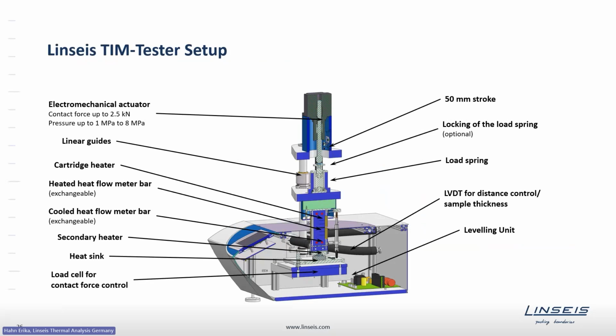On the slide you can find a more detailed sketch of the TIM tester with its components. The main part here are the meter bars, which contain heaters inside, being able to heat up the sample. In between, we clamp the sample. During the measurement, we also track the sample thickness using an LVDT. A further important part of the TIM tester is this actuator on the very top, so that we are able to control the contact pressure onto the sample. Similar to the THB method, we want to guarantee a good contact between the sample and the meter bars. You also see the pipes going to the external chiller, being able to cool down the lower meter bar.